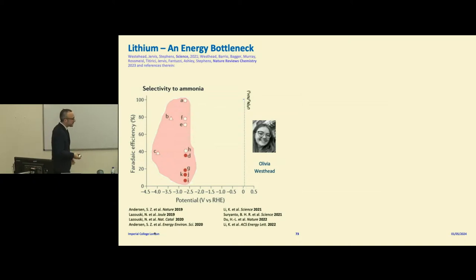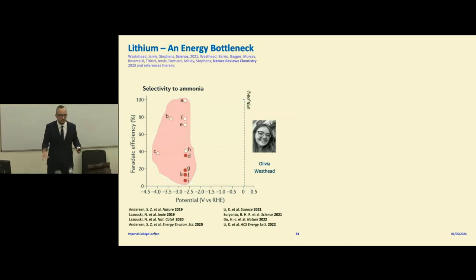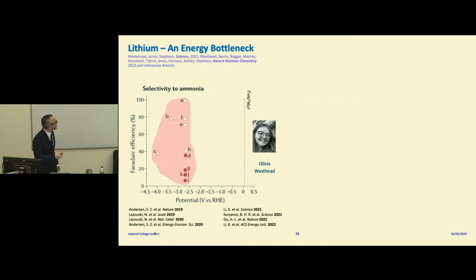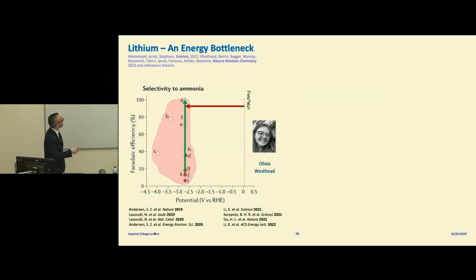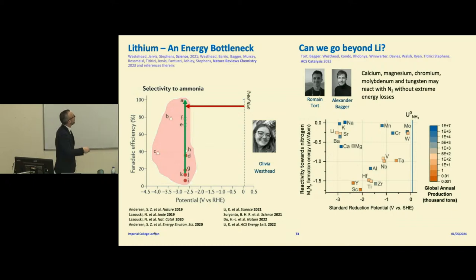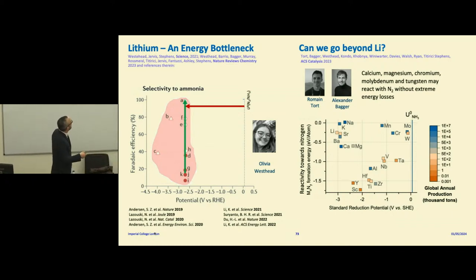And that's because you need to electrodeposit lithium. Lithium wants to be a salt. It doesn't want to be in the metallic state. And this sets a huge bottleneck on the reaction, especially if you want to use ammonia as a fuel. So I again turned to my theorist collaborator, Alexander, and also to Romain Tort, who's in the audience. We thought, what other alternatives could there be?